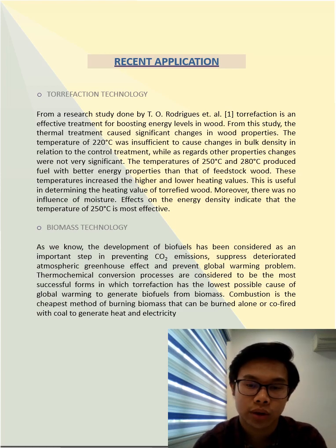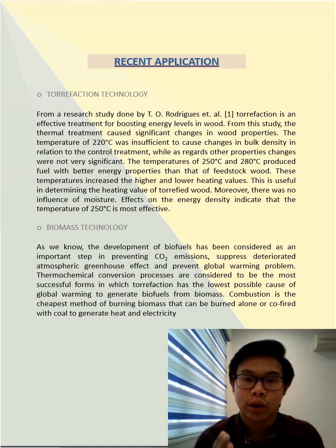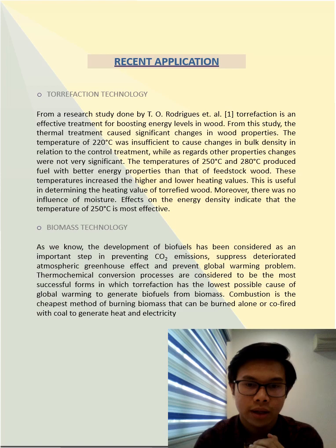The temperature of 220 degrees C was insufficient to cause changes in bulk density in relation to the control treatment, while as regards the other properties, changes were not very significant. From this sentence, we can see that the wood energy content will be enhanced after the torrefaction process is applied to the wood. Okay, next, the temperatures of 250 degrees C and 280 degrees C produce fuel with better energy properties than that of the feedstock wood. These temperatures increase the higher and lower heating values. This is useful in determining the heating value of the torrefied wood.